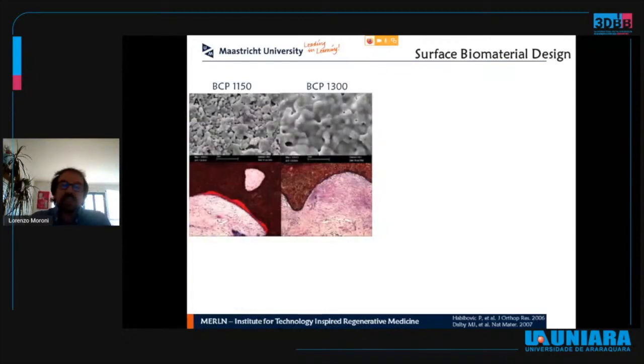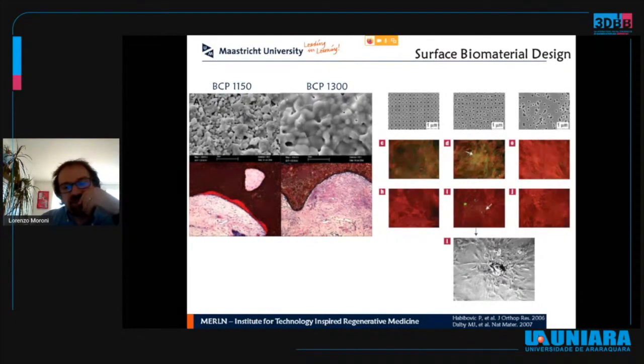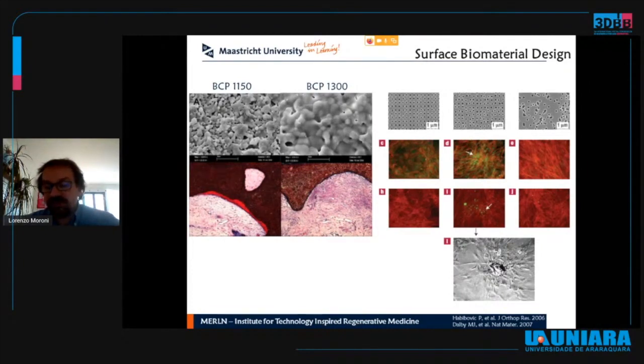Now, what do we actually need more in terms of instructive characteristics? If we look, for example, at one of the most performing synthetic materials in terms of osteoinductive character, that of ceramics, we have seen from the literature in the field that the microtopography of such ceramics can make a drastic difference, changing the same ceramic chemistry from non- to pro-osteoinductive. This has also been somewhat studied in polymers by the group of Matt Dalby a number of years back, where they showed that the creation of nanotopography with specific size and also specific disorder resulted in an increase of osteogenic markers in vitro.